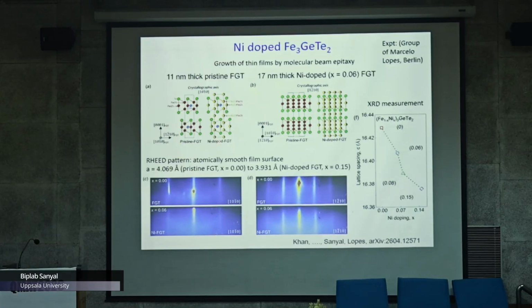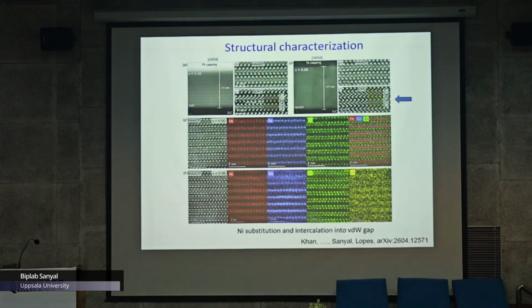What you see in this nickel doped FGT is that there are nickel atoms here in the van der Waals gap. If you dope with nickel, you see that the lattice parameters change. The a lattice parameter and the c lattice parameter change with nickel doping. I will just highlight certain things, not go into experimental details. But if you do this HAADF and this particular experiment, iDPC, you see the signatures of these atoms in the van der Waals gap.